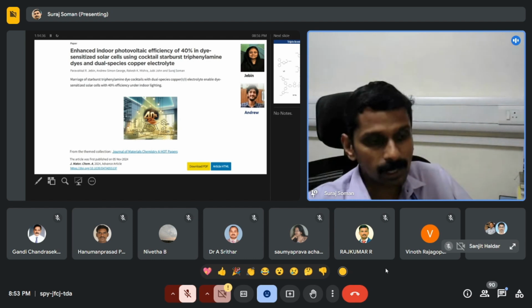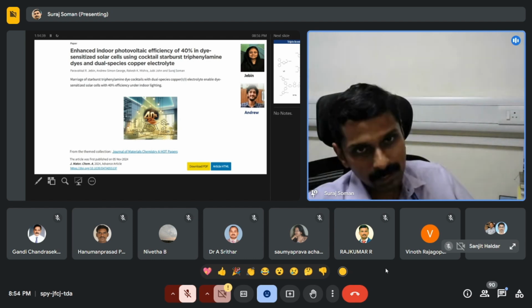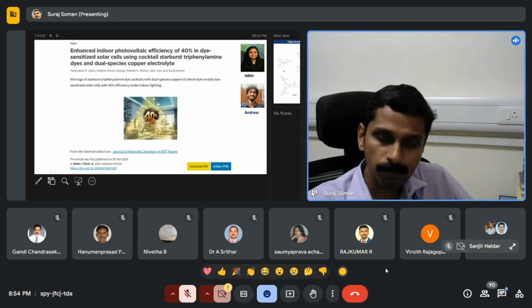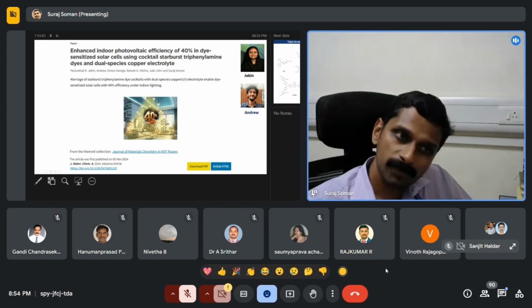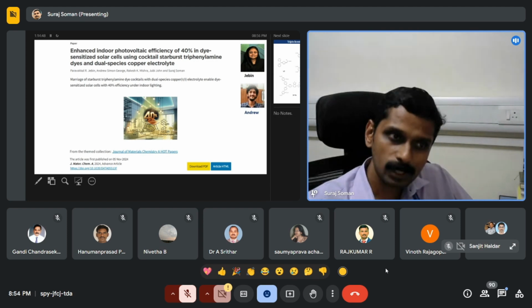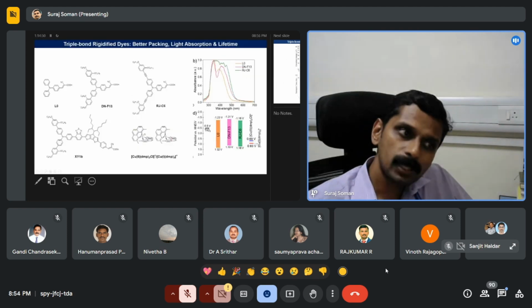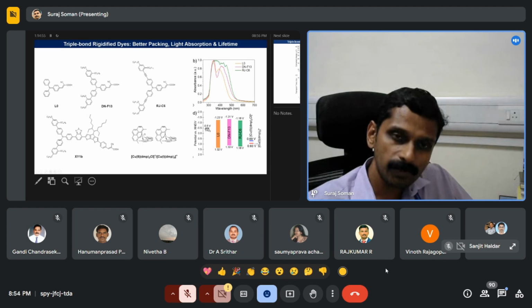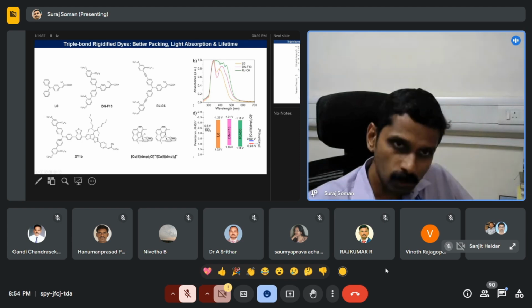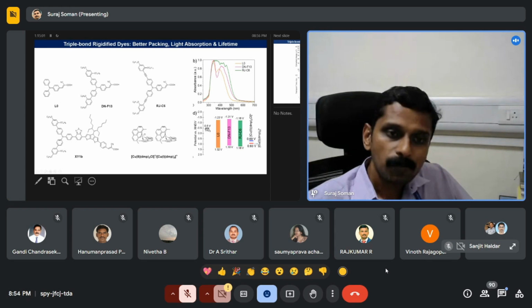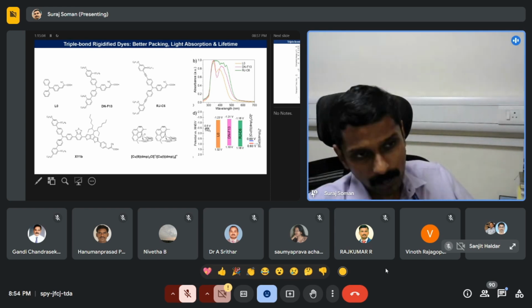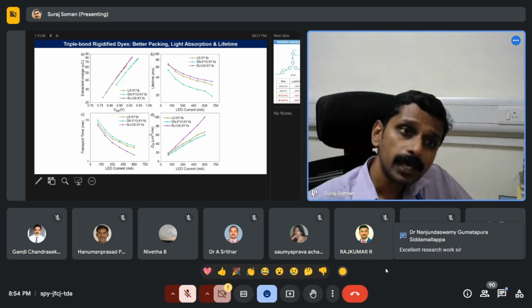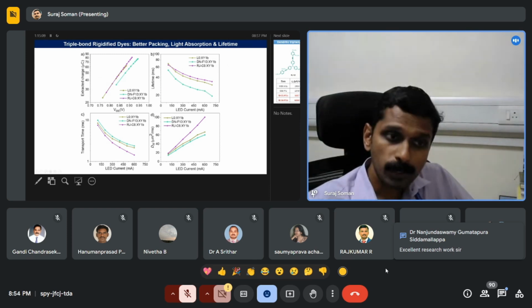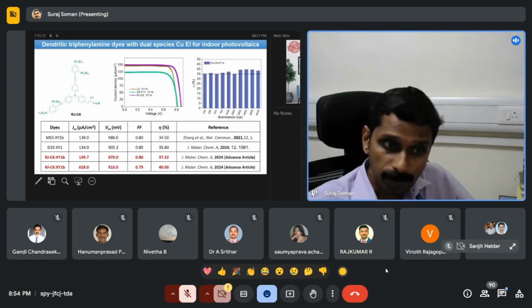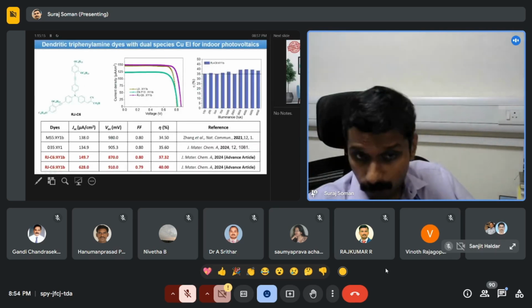It's still in the advanced article version, where one of my students, Jebin, introduced a new triphenylamine dye. So we use the same dual species electrolyte, and along with the dual species electrolyte, this RJC6 is a co-sensitizing dye that we have developed in our group. And with that particular dye, in combination with the XY1B, we are able to make a very uniform layer of TiO2. And that helped in having a better lifetime, a lower transport time, and a higher diffusion coefficient. And finally, realizing the record efficiency of 40%.